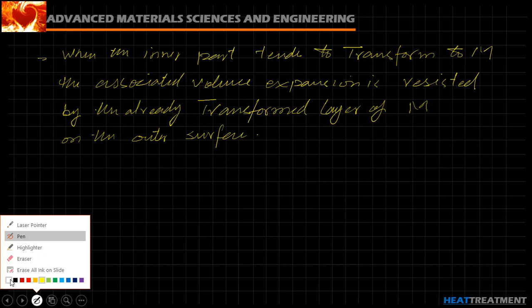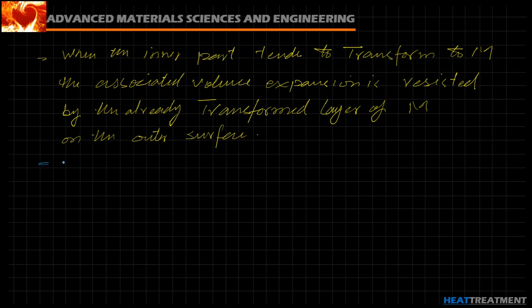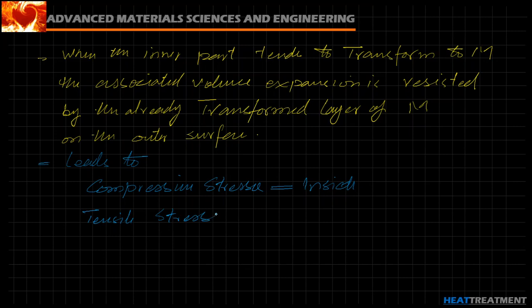As a result, this leads to the formation of stresses, compressive stresses which are acting inside, and the tensile stresses which will be acting outside.